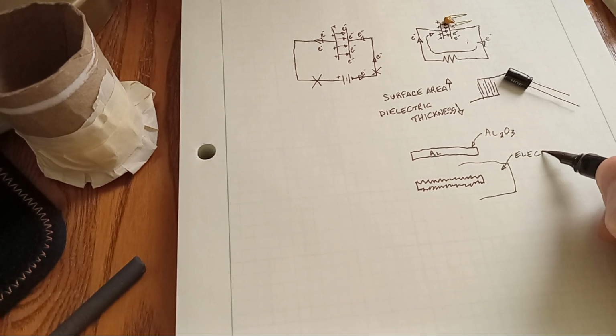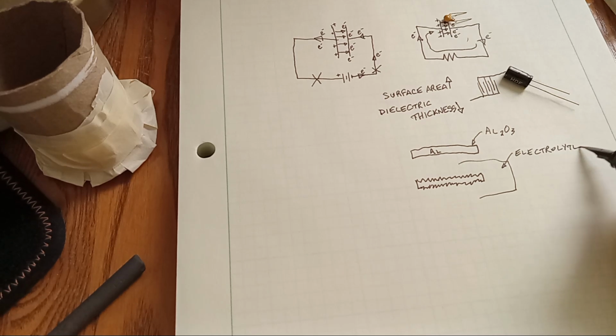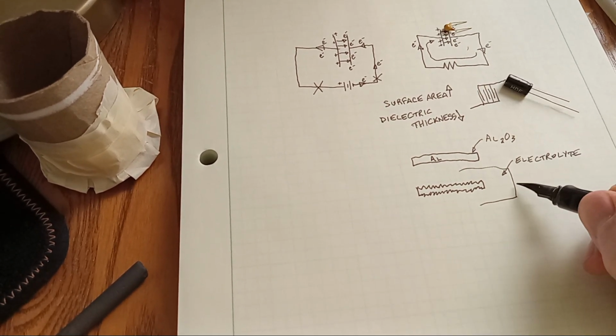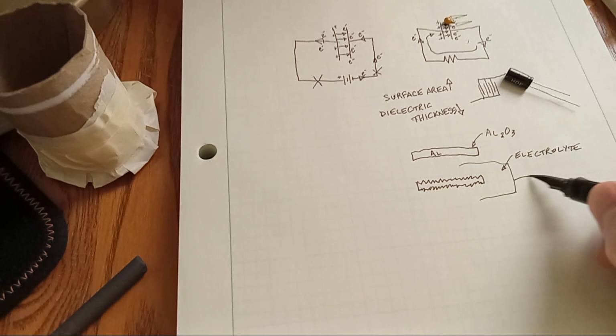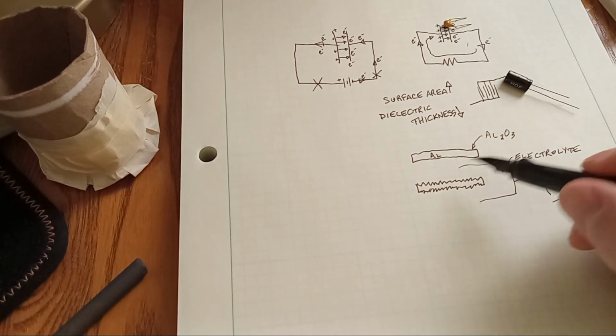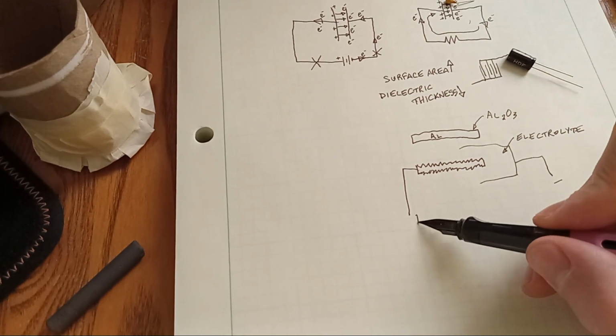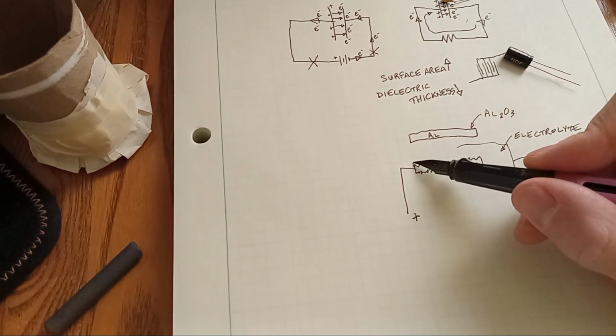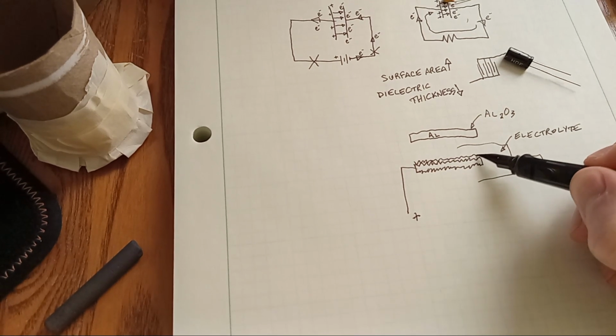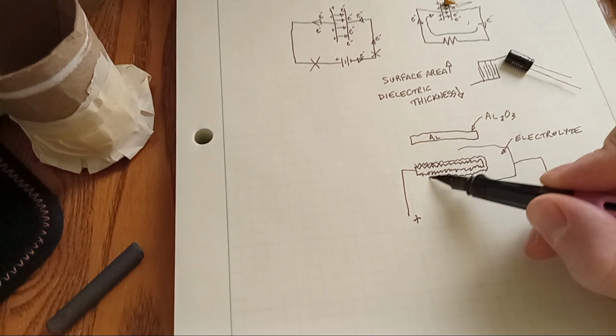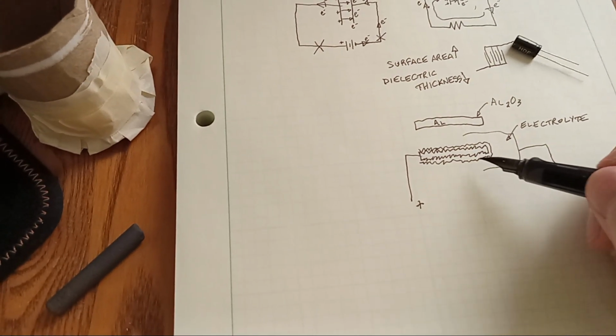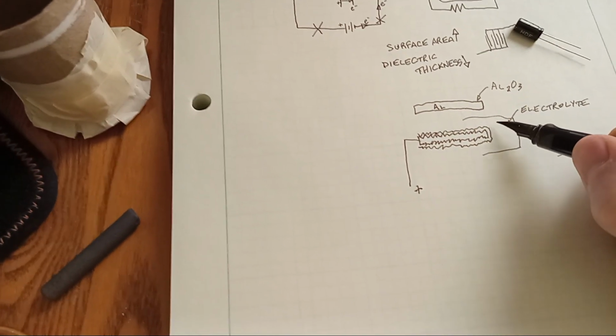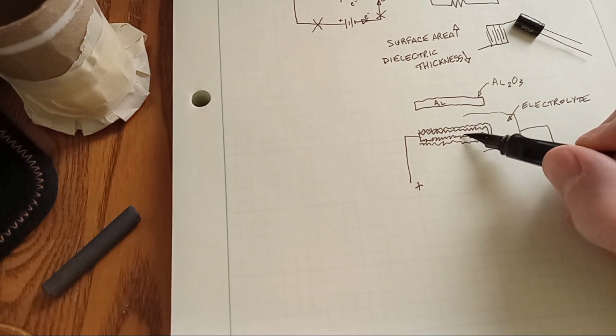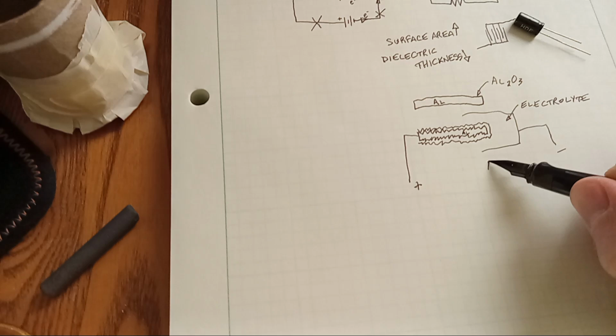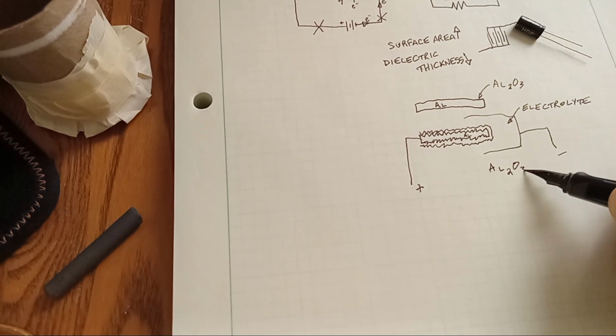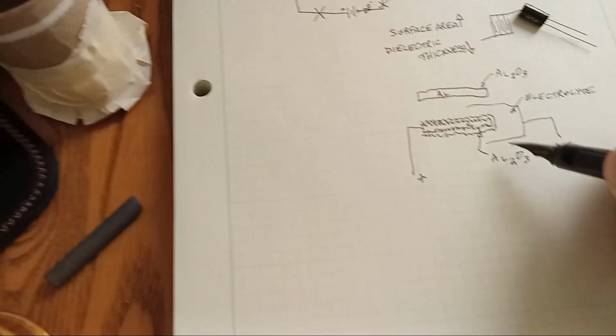That said, if you put some electrolyte here and then connect it to the negative terminal of this whole device, and connect the aluminum to the positive terminal of the whole device, the aluminum will grow a thin layer of oxide, which is non-conductive, on top of the ragged surface which you have already produced by electrochemical etching, and this forms a capacitor, because the electrolyte is one plate, the aluminum is the other plate, and the dielectric is the aluminum oxide, which has formed in a layer around the aluminum electrode.